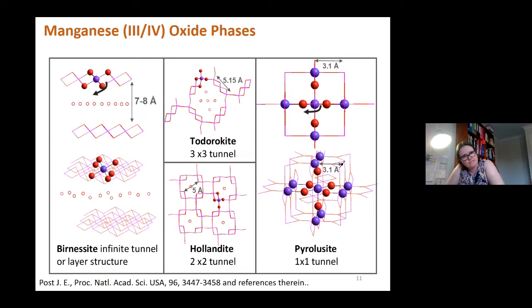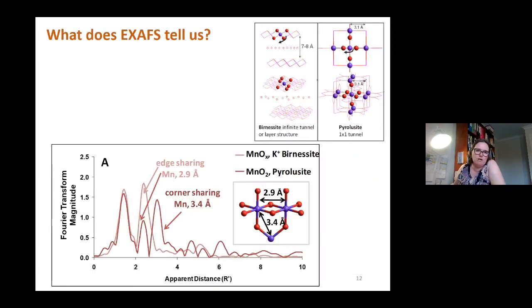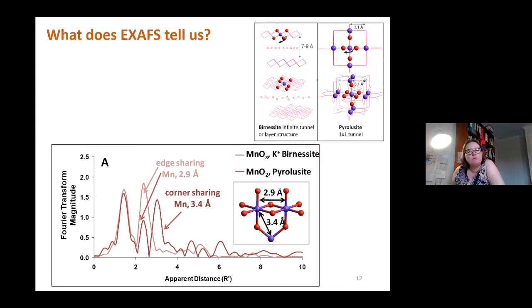I was able to tell that the material was likely to be a metal oxide. I wanted to use XAS to determine which metal oxide it was. If we know the oxidation state — in this case around 3.8 — we can isolate the structures we think it could be and tell from the XAS which one it is. The layer structure birnessite produces quite a distinct XAS compared to pyrolusite, which has a rutile-like structure. Based on this, we learned the material very likely has a layer structure similar to birnessite.